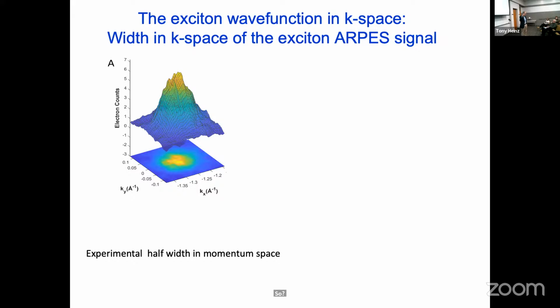Well, one of the things you think of immediately is, you're doing this experiment at finite temperature. The excitons will have some kinetic energy. They're going to be moving around. But when you calculate how much momentum broadening that would give rise to, it's absolutely negligible compared to what we see. So you kind of double check, is this really correct? This is the experimental resolution. It's really far below what we're seeing. The answer is yes. So does anybody know why you might see a finite width in momentum space if you're emitting from these cold excitons that are not moving very significantly?